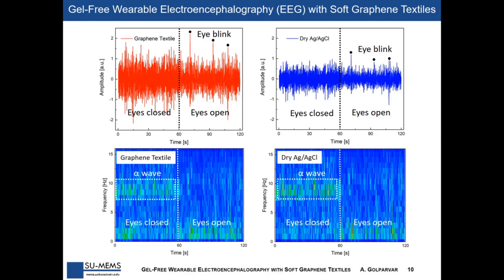And the alpha waves usually oscillate between 7 to 13 hertz in the frontal cortex when the subject is resting, and disappear when the mind is active. The figure below illustrates the short time Fourier transform of the recorded signals, where alpha rhythms can be tracked between 8 to 11 hertz when the eyes are closed and disappear subsequently after opening the eyes. This sharp alpha wave disappearance in the transition between eye closed and open state certifies the successful acquisition of alpha waves and EEG signals from the forehead using graphene textiles.